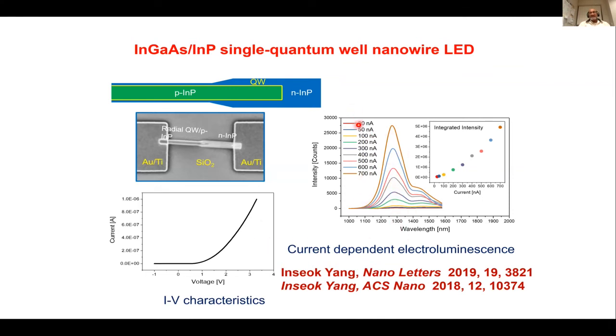So you can see that as you increase the amount of current through this LED, this particular device, you end up getting brighter and brighter light. But you also see two emission peaks, mainly because the quantum well which is sitting on the top of the nanowire has a different thickness and composition from the quantum well on the side of the nanowire.